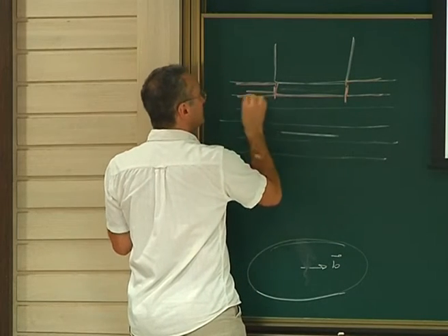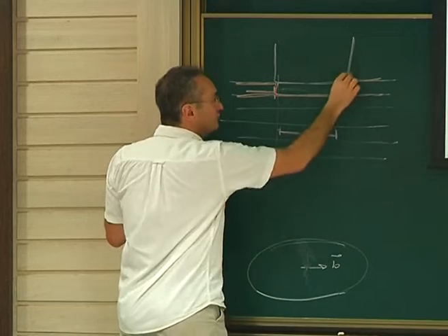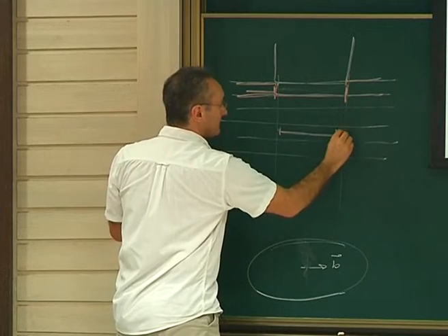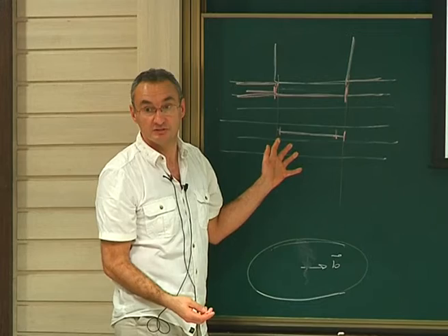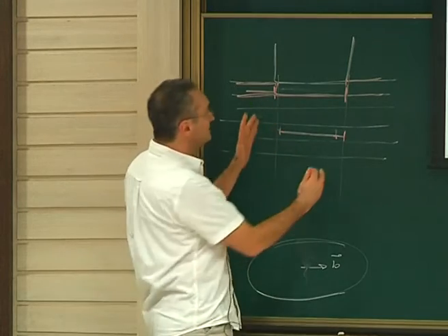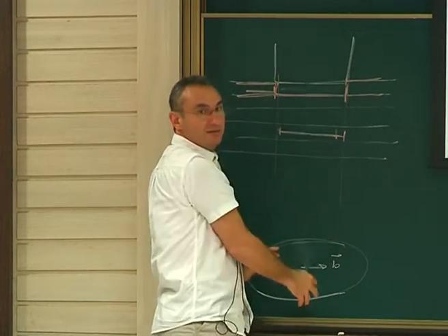Let's say that you have your plane which is missing, and here you have your interstitial loop. And they have to be on the exact same cylinder. They have to be exactly on the same cylinder in order to keep the volume constant. Since you want to be conservative, if this is missing here, it has to be there. So they should be aligned in the same cylinder.